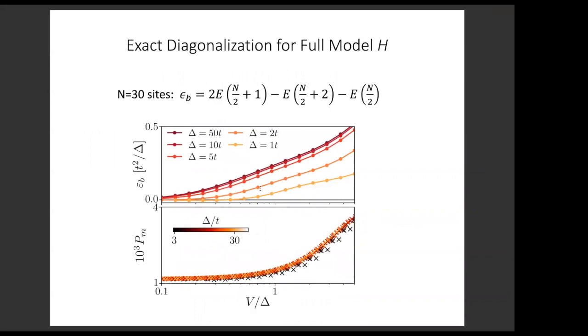So this again shows that the pairing occurs in such a simple model with purely repulsive interactions, and this sounds very unusual, but we also check this. So my student Val did an enormous amount of diagonalization study. Here I'm showing the binding energy from a full calculation of the entire honeycomb model with 30 sites, and again you can see the binding energy and pairing correlation develops as you increase V.